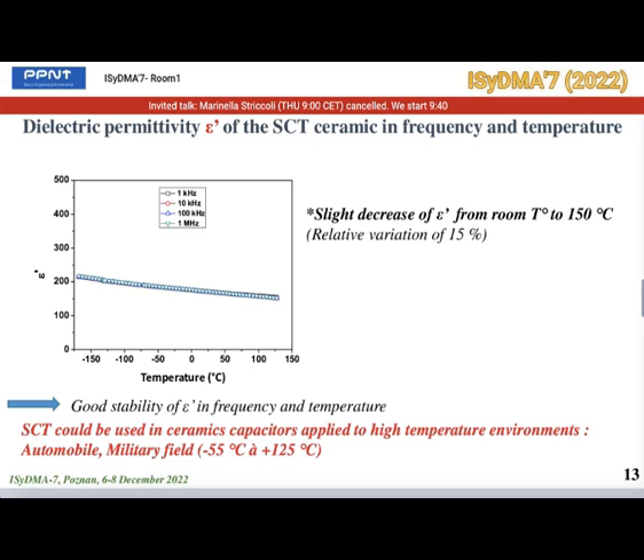If we expand the scales, we see that the dielectric permittivity presents a slight decrease from room temperature to 150 degrees Celsius for all the frequencies, and no phase transition is observed. The SCT gives a relative variation of 15% up to 150 degrees. The stability of the dielectric permittivity with respect to temperature is very interesting and shows that SCT could be used in ceramic capacitors applied to high temperature environments such as the automotive or military field, for example.